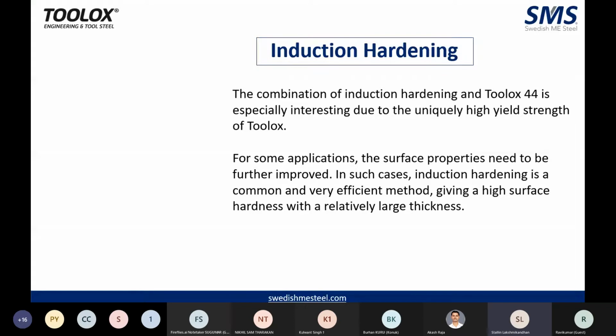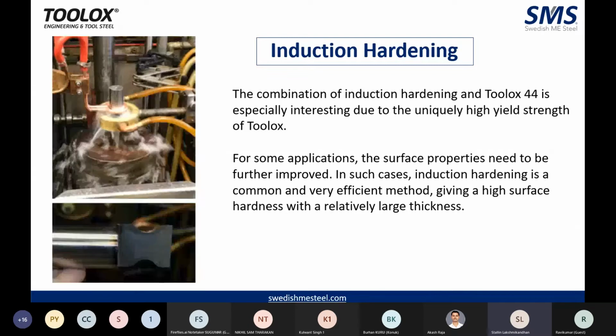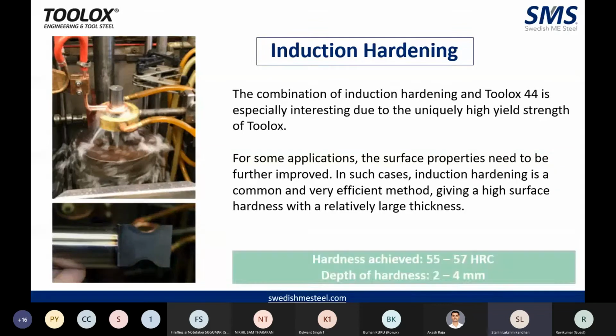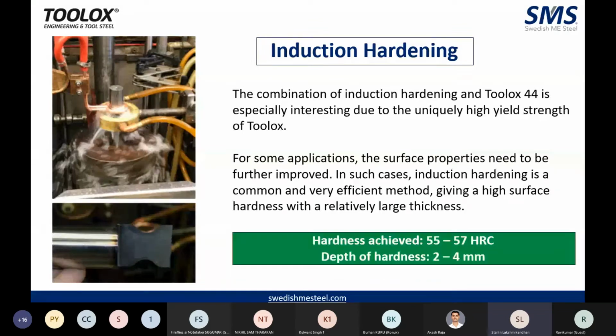So first we'll check out induction hardening. This is a process in which the case depth can be improved up to 3 to 4 mm. The hardness achieved is around 55 to 57 HRC. The depth of hardness that you can achieve is 2 to 4 mm.